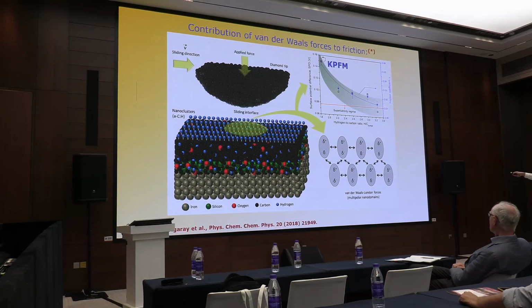Here you can see this is the surface. Also we measured with Kelvin probe force microscopy. There is an agreement between this and the friction coefficient. The surface potential is higher, the friction is higher, and when we decrease this surface potential, the tribocharges, we also reduce the friction coefficient. And the most important point is this, the lowest, this is the superlubricity regime. This point is under the superlubricity regime. This thin film is superlubricious. This is when we have the highest hydrogen content on the surface. This sample has the highest hydrogen content.